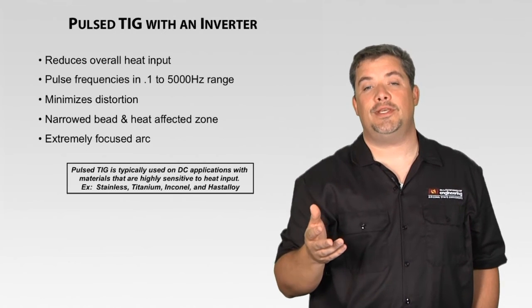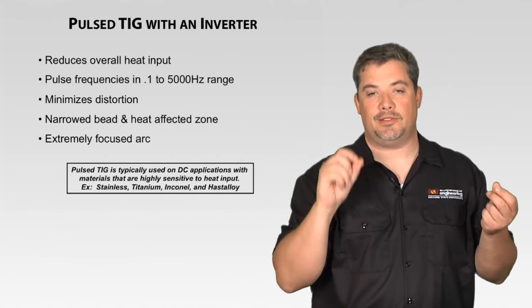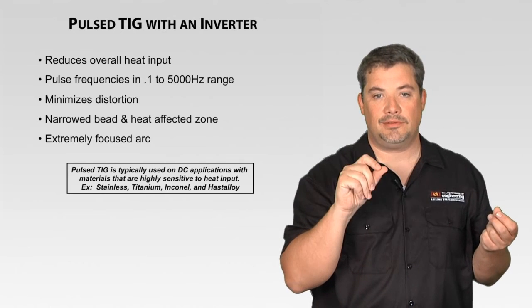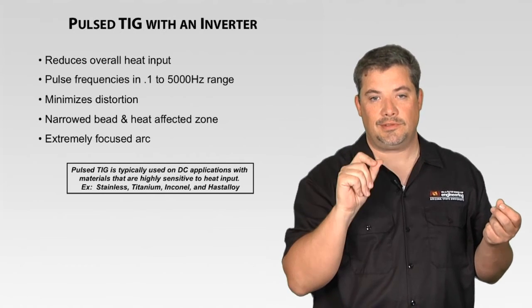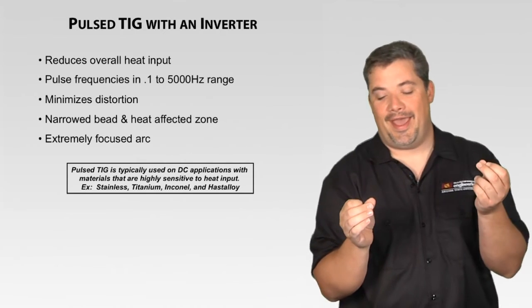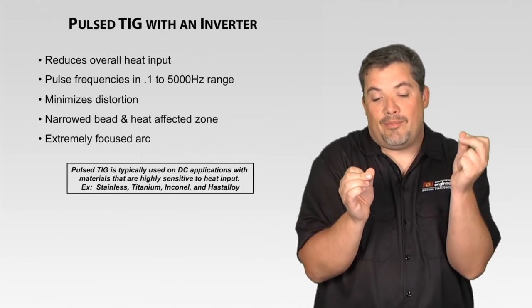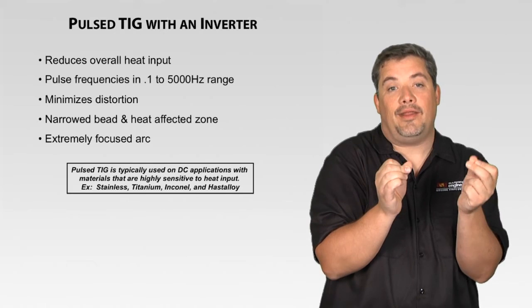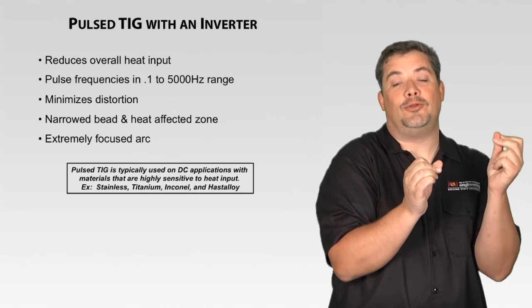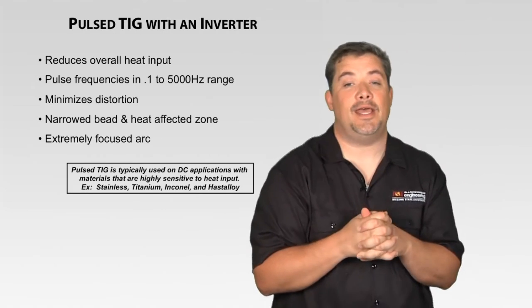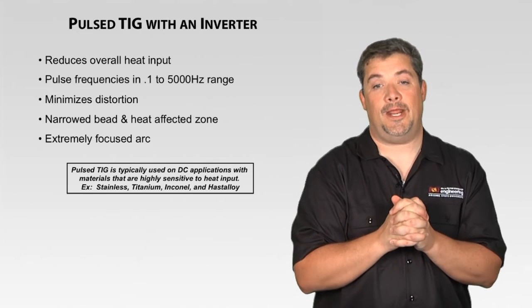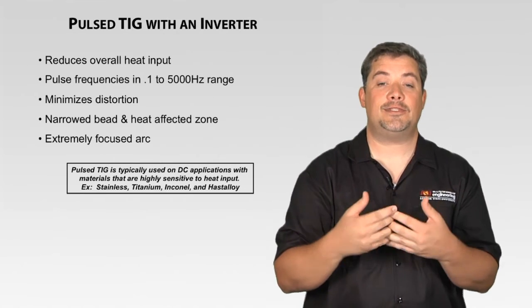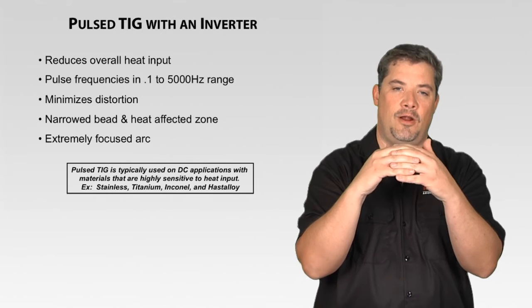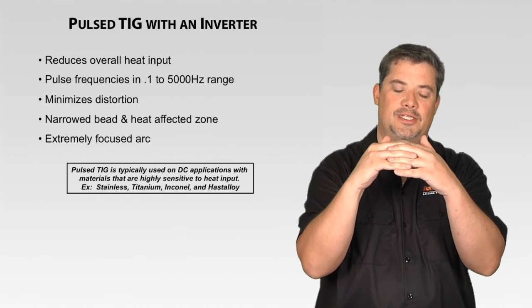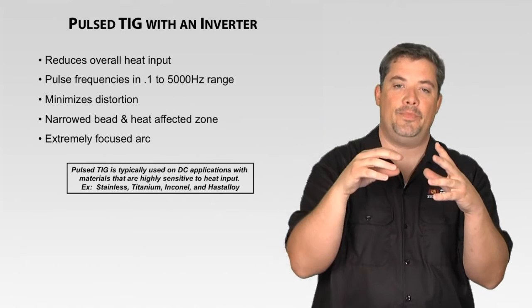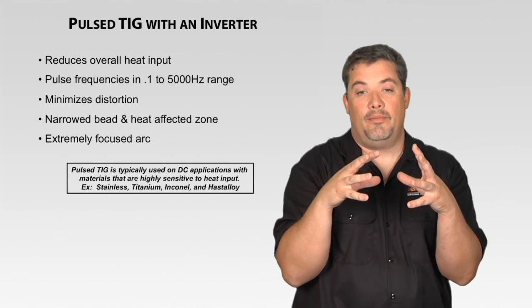Low pulse frequencies, let's say around 1 pulse per second, there's my example for you. And I can actually just time my filler rod adding with that, and I could use it for maybe a learning tool. 10 pulses per second is actually a pretty good setting for things like Inconel and Hastelloy, where they have this real hard, heavy surface tension. They're very sluggish. But when I pulse them, it actually makes it easier to weld them.